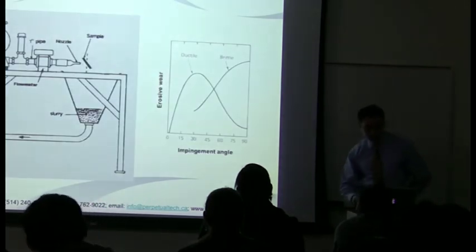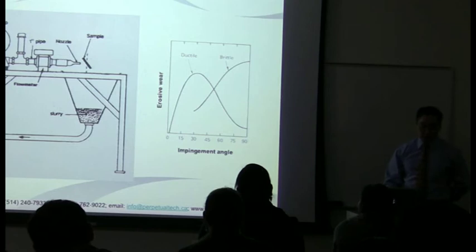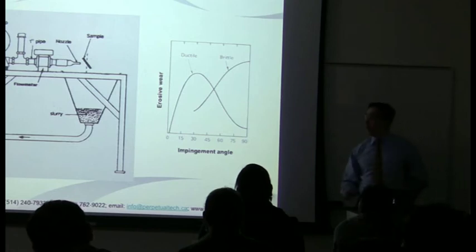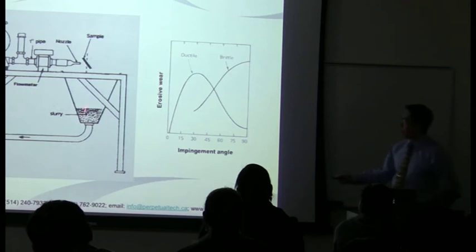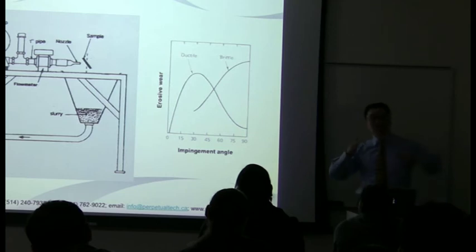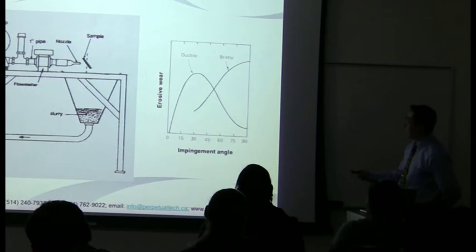We also carried out some slurry erosion tests. This was carried out at the National Research Council of Canada. And basically, you pump your slurry through a nozzle, you accelerate that onto your coated sample. You can change the orientation of your samples so that you can get different impingement angles. And that's really important. And the reason why is shown here.